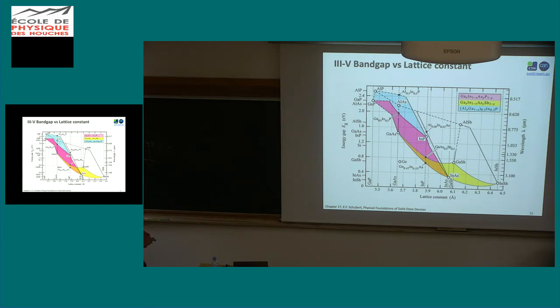But of course, you can also alloy gallium arsenide with indium phosphide, and whenever you achieve more or less 50-50% of gallium and indium, you will end up again with a crystal that is lattice matched with the gallium arsenide.